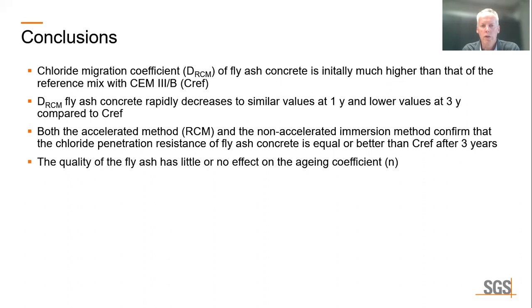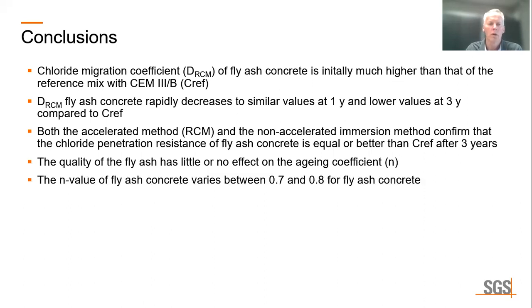And that the quality of the fly ash has little or no effect on the aging coefficient. And finally, that the n value of fly ash concrete varies between 0.7 and 0.8, and these values are in very good agreement with the National Dutch Guideline on service life calculation of reinforced concrete mixes.